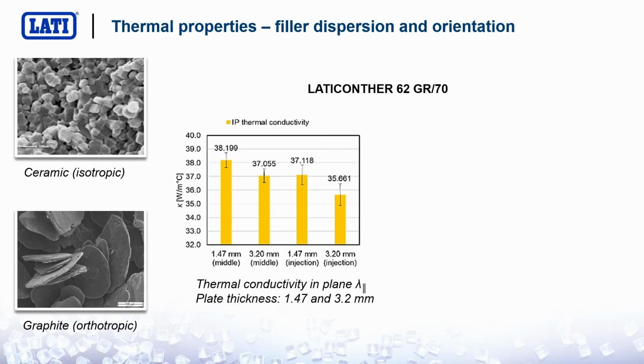This is the thermal conductivity in plane. In plane meaning that the flakes are oriented on the plane and we are actually measuring the thermal conductivity in the plane direction. As you can see, the numbers are really very high. Thermal conductivity of a graphite-based fully oriented plastic can be as high as 35 to 40 watt/meter Kelvin. The higher the thickness, the lower the in-plane conductivity.